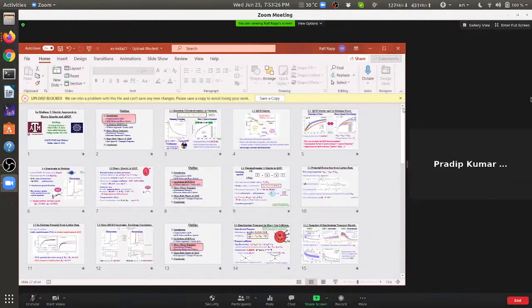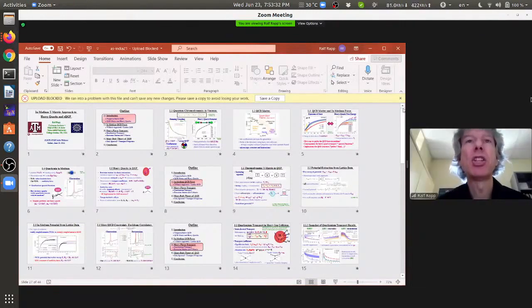Okay. Sorry, Ralf, I missed it. So you mean that the imaginary part is negligible? No, quite the contrary. There are a number of recent lattice calculations which find very large imaginary parts, much larger than you would expect from perturbative QCD like HTL or so. Much larger, and at the same time the real parts are also larger, and that really goes in the direction of what we would call the strongly coupled solution.